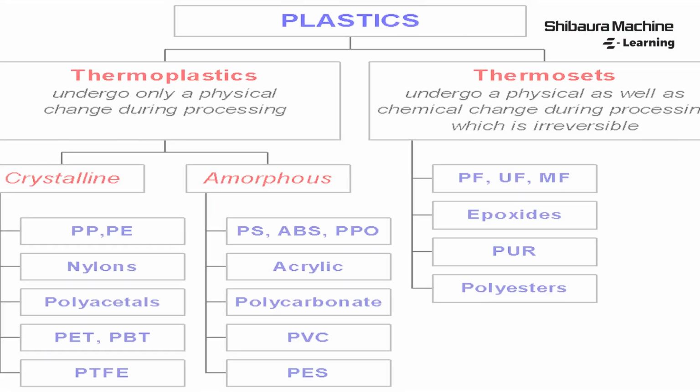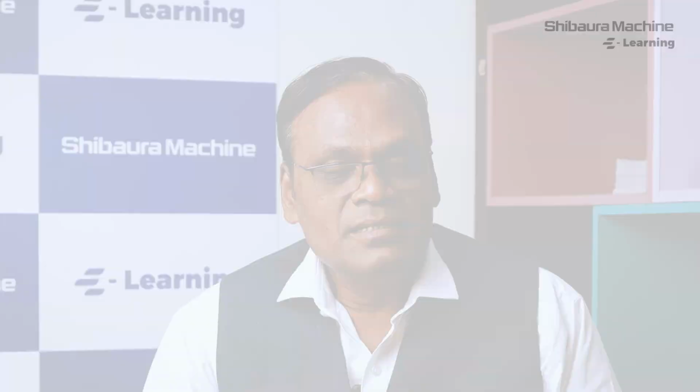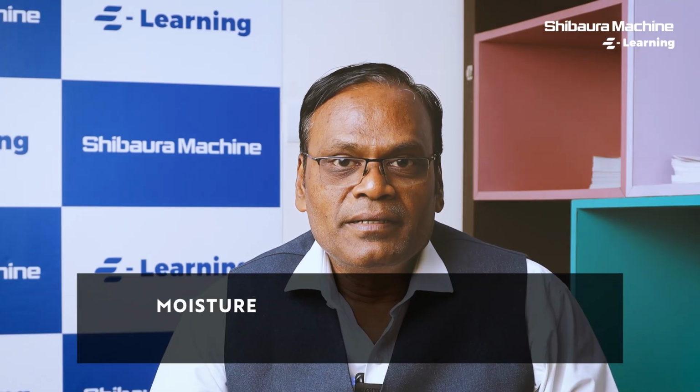Using the right polymer is paramount important in avoiding bubbles in a molded part. In today's scenario, many new polymers are being used. Selecting the right parameter is important in concluding on the polymers. Moisture in polymer leads to formation of bubbles in molded part. If the material is hygroscopic in nature, the moisture settles in the polymer. It needs to be pre-dried properly before using on injection molding machine.